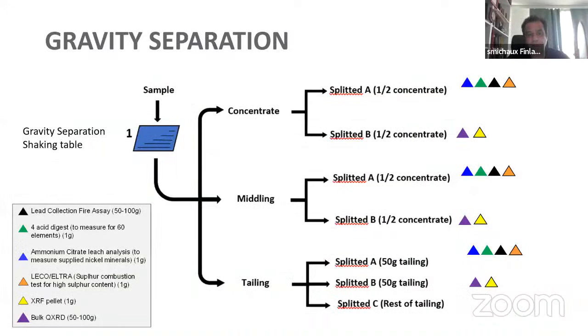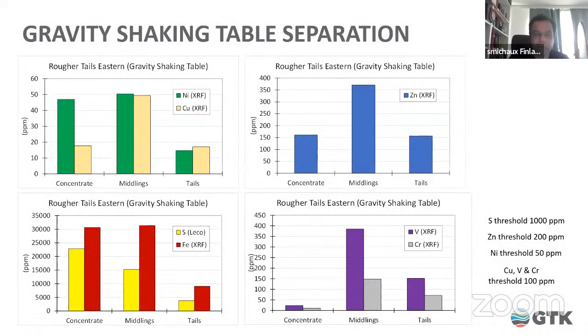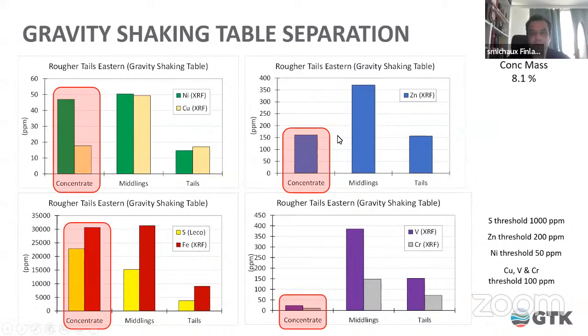So here's gravity separation. We went through a shaking table, and we've got the concentrate, the middlings, and the low mass tailings. And we will collect those fractions, and we will characterize each one. So here's the data. So the concentrate represents about 8% of mass. So, okay, anything more than 10%, it's not really practical anymore. So it helps. And again, we are removing some material, but it's not actually enough.